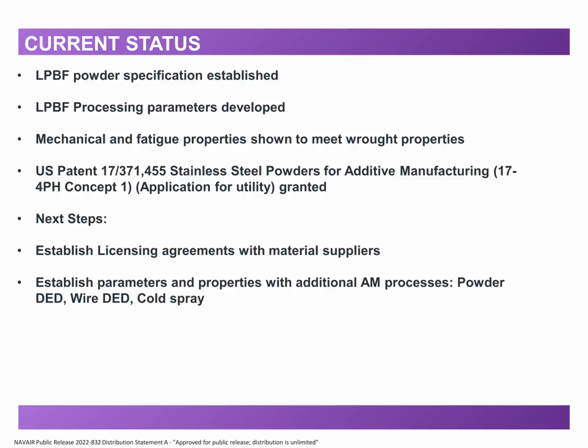The current status of the program is shown. The laser powder bed fusion specification has been established. We were able to develop a robust set of processing parameters to support printing to meet the properties without the post-thermal treatments. We were able to achieve mechanical and fatigue properties to meet the wrought properties of 17-4. A U.S. patent has been issued for that particular novel alloy.